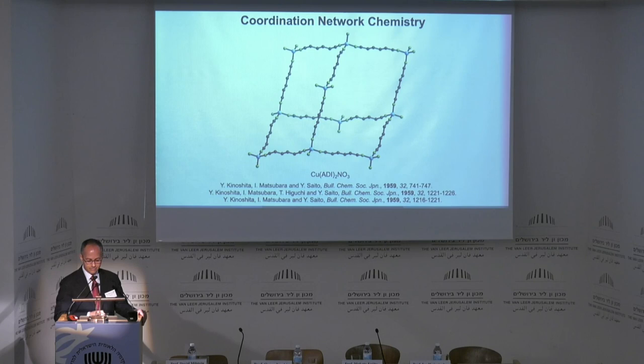So that's that. I would say this is the first example. I'm not saying that it's robust. I'm just saying this is an example in the literature where it was possible to link a metal ion with a dinitrile. And I want you to remember that this is a neutral linker. So that's making this copper 1 nitrile bond a weak bond, about 60 or 70 kilojoules per mole. Keep that in mind because it will become relevant later as to why MOFs emerged.